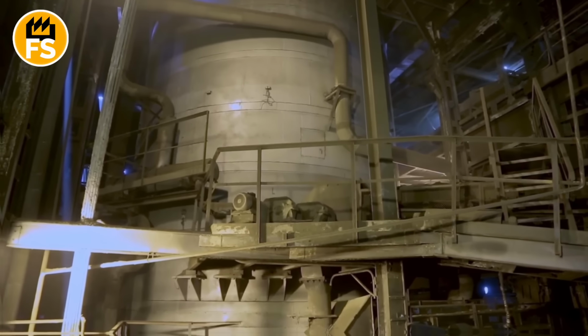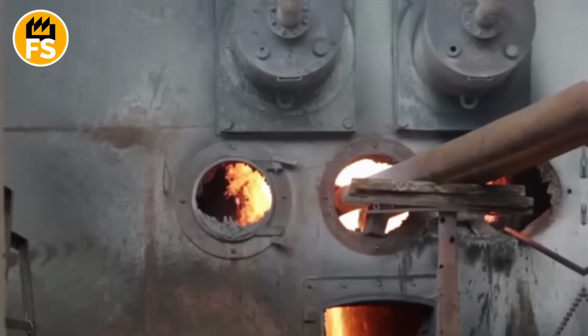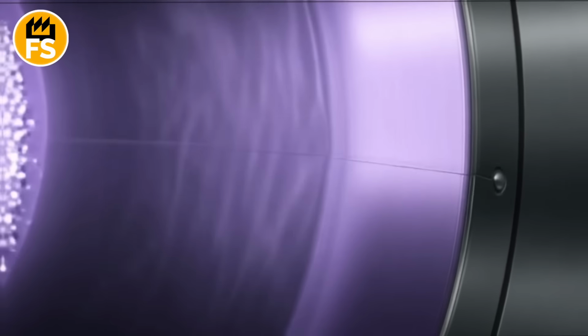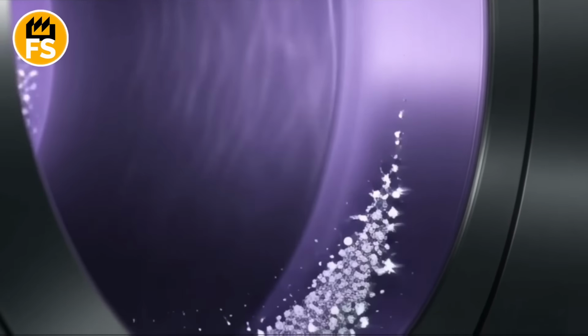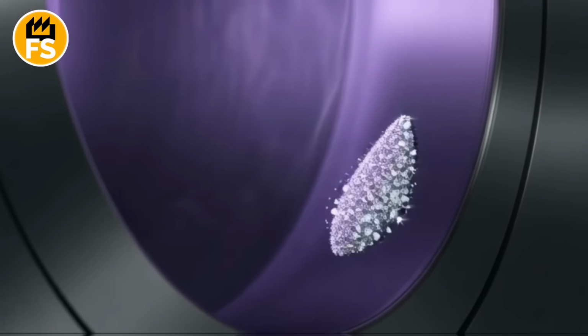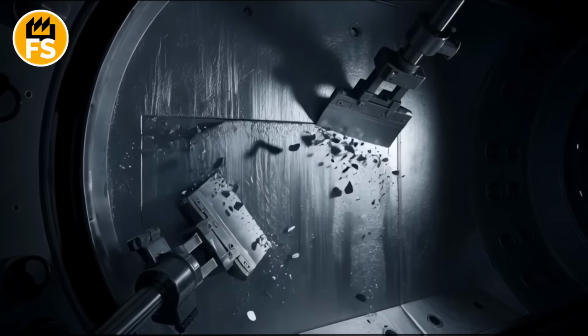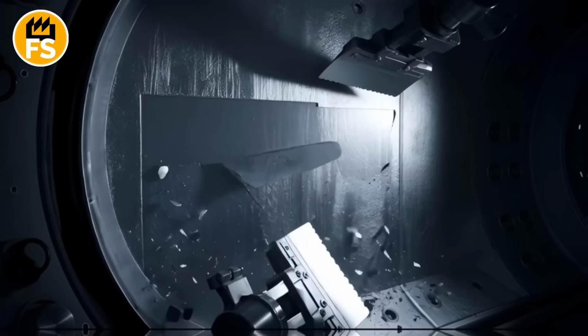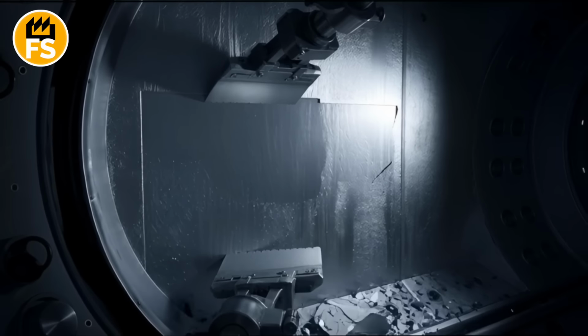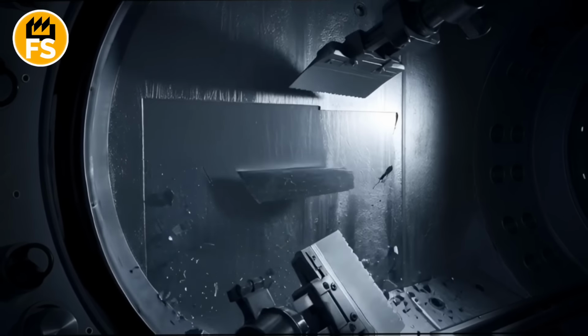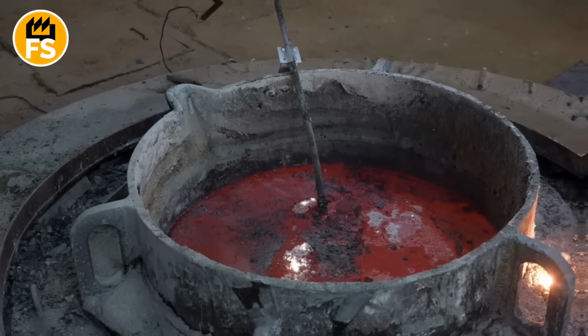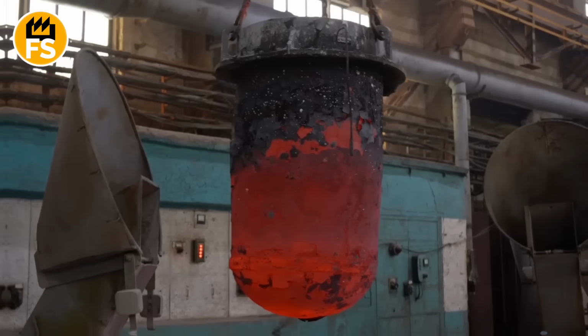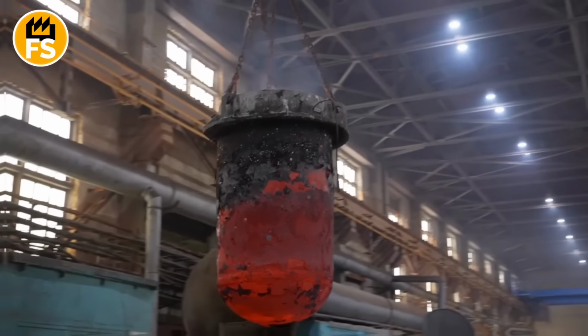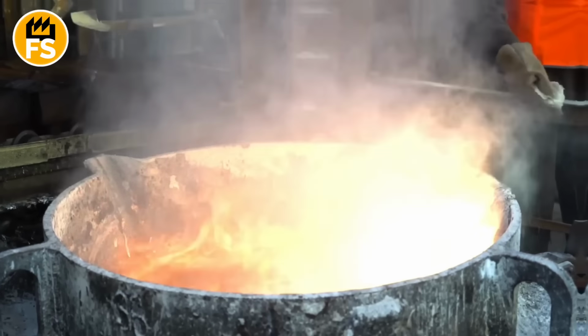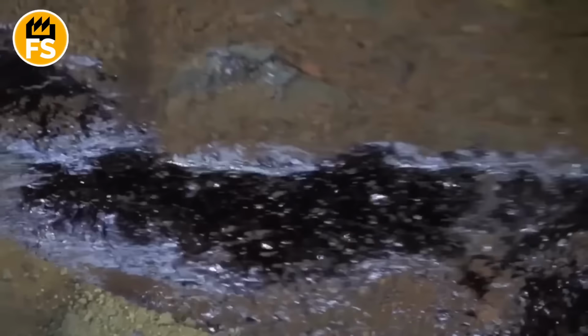The chamber looks like a vertical steel cylinder, with cooled walls from the outside. Inside, magnesium vapors meet the cold surface, and the metal condenses as a shiny coating that resembles silvery frost. This coating gets periodically scraped off by mechanical scrapers or robotic manipulators operating in an environment with minimal oxygen access. The collected metal goes into protected containers, where it's melted again to remove residual impurities. The melting crucibles look like deep wells filled with glowing silvery molten metal, and extraction systems constantly work above them, protecting the metal from contact with air.